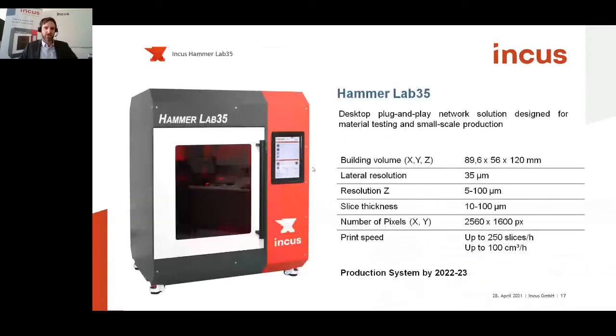Here, almost at the end of my presentation, you see the printer we're offering at the moment. It's our laboratory system, the Hammer Lab35. It has a building field of 90 × 56 millimeters and a resolution in the printing field of 35 microns. This is the resolution of the imaging system, of the projector unit. Depending on the powder, we can print with a layer thickness from 10 to maybe 100 microns, but it's always dependent on the powder. If you say the building field is too small for your application, don't worry. We will come up with a production system with roughly 200 × 200 in the following years, and we will update on that. But we think the laboratory system is a good way to start material development, get used to the LMM manufacturing process, and then upscale.